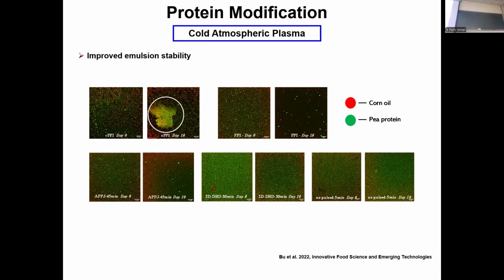We formed a coarse emulsion and then a fine emulsion by two-stage homogenization, and we stored the emulsion under accelerated storage conditions for 10 days. With the commercial pea protein, the emulsion formed aggregates. This is CLSM, by the way, confocal laser scanning microscopy, where we stain the protein green and the oil red. You can see that the commercial protein aggregated, whereas all the other emulsions where the protein was subjected to cold plasma showed no change. So we had a regular emulsion throughout storage.